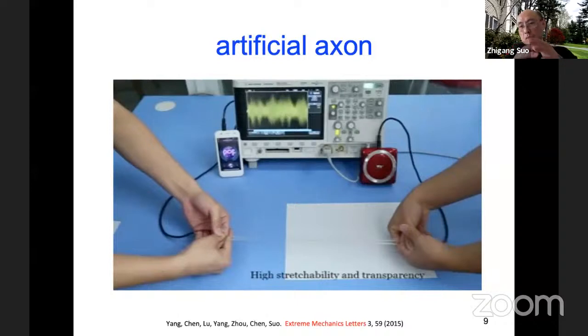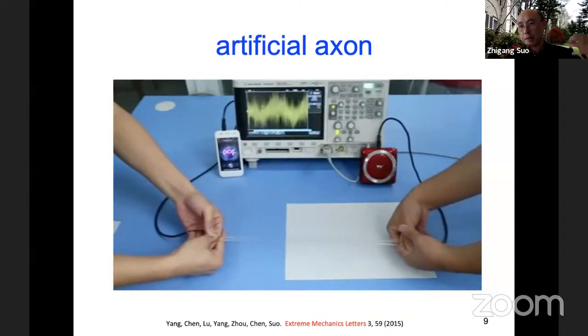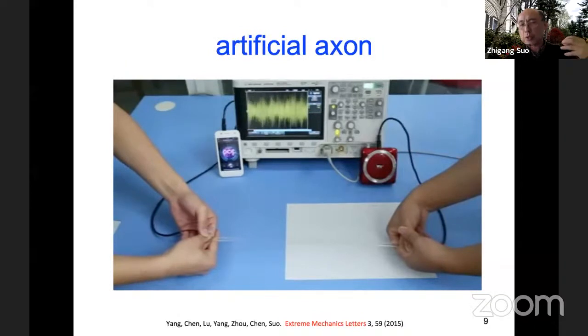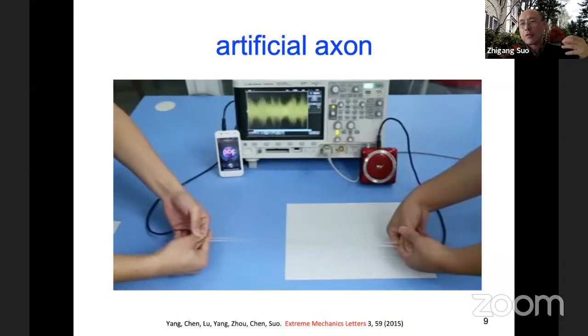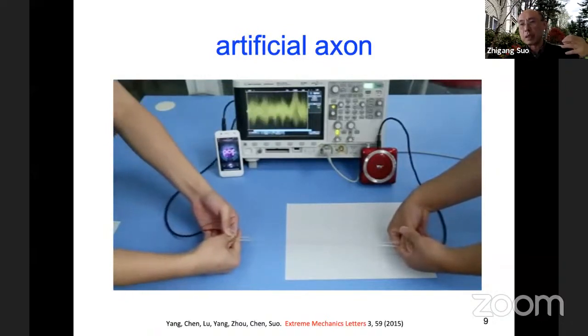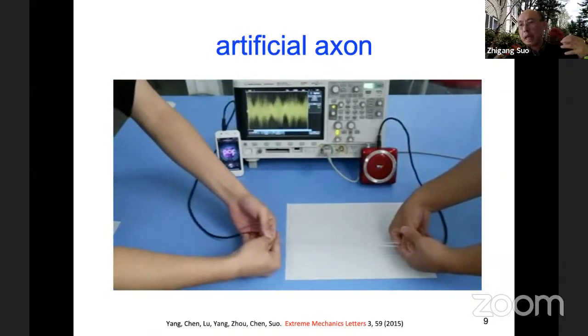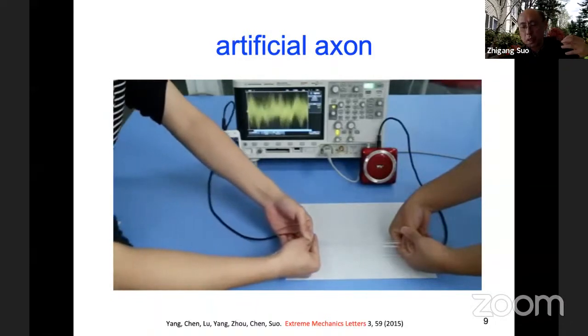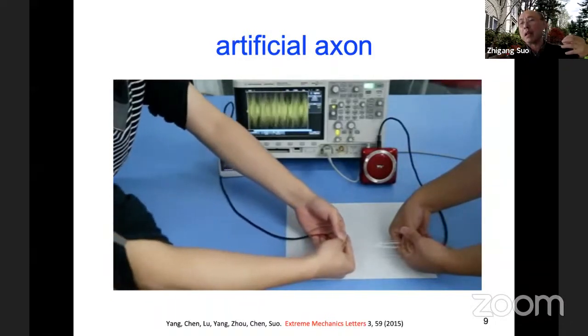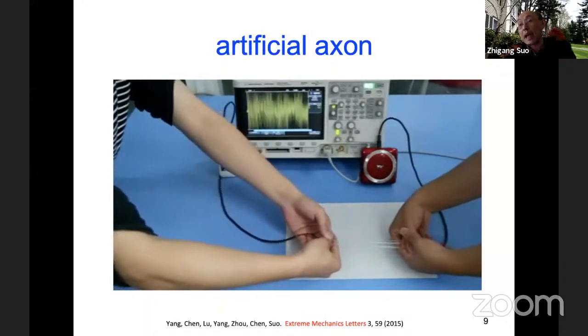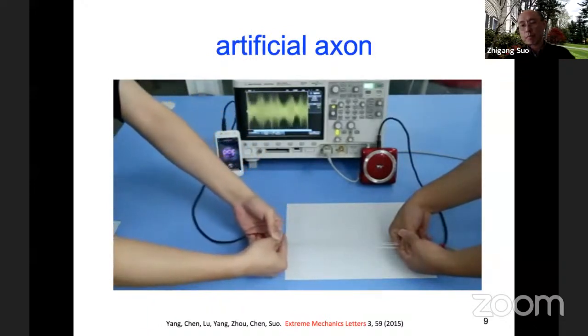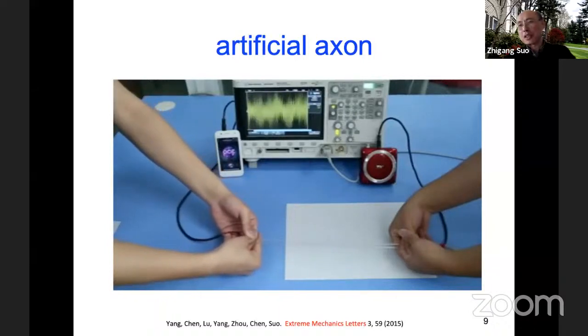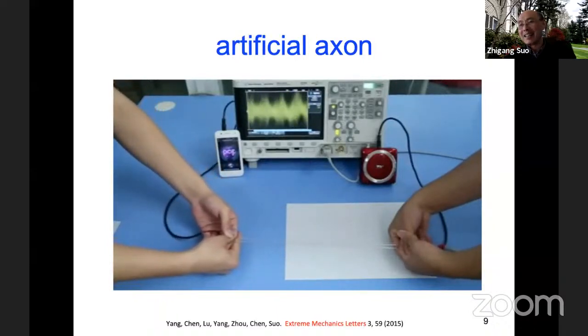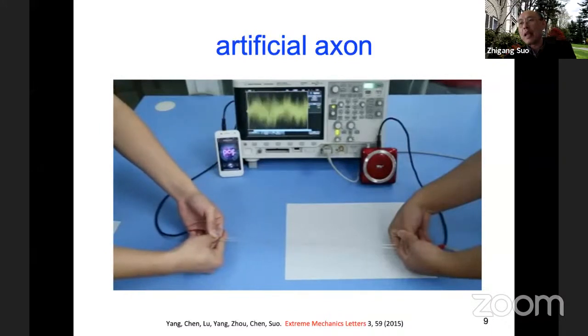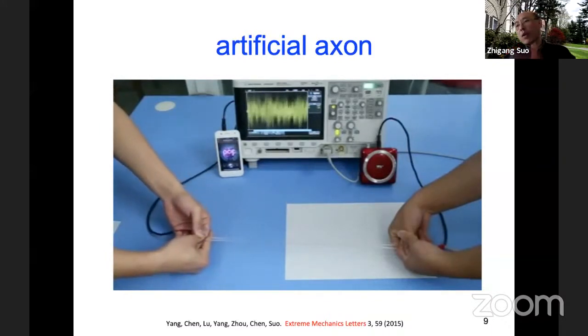The reason we can do better than axon in terms of frequency: for human music signal is about 20 kilohertz. Our thing, we measured experimentally, electronically, we can pass 1 million hertz signal with fidelity. The reason we can do better is because our hydrogel has a lot more ion than salty water inside the body, orders of magnitude.